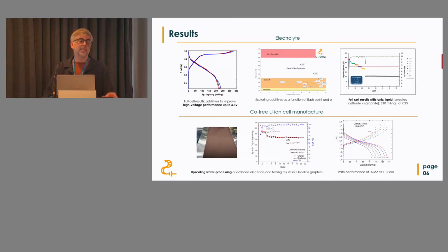Also, we are looking at these additives to increase the stability, as I mentioned, as a function of the flash point and a function of the conductivity for these electrolytes in order to get good performance at high C rates. And also, we are obtaining good results with ionic liquids, so we are managing to push the capacity of the cells up to 210 milliampere hour per gram at C/3 using ionic liquids.